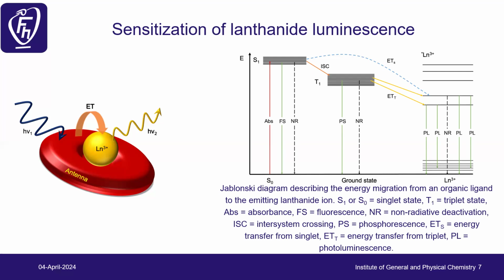One is radiatively, known as fluorescence, non-radiatively, or to go through the intersystem crossing to the slightly stable triplet state, from where the same electron has three ways to relax. One is radiatively, known as phosphorescence, non-radiatively, or at the end, to transfer its energy to nearby lanthanide, where the 4f electrons are excited from the ground state to the excited state, and then they can relax. At the same time, relaxing non-radiatively, and from here the 4f electrons can be relaxed radiatively, what is known as photoluminescence, or non-radiatively.